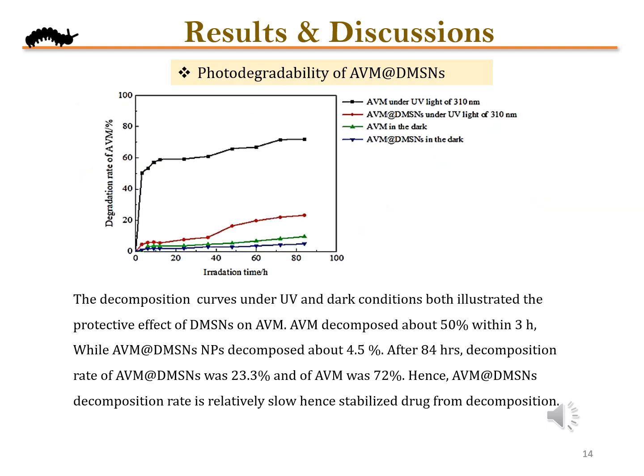As we know, the AVM is a photosensitive material. It was necessary to check the photosensitivity or the photodegradability of the AVM loaded DMSNs, and from the results it was shown that the decomposition curves under UV and dark conditions both illustrated a protective effect of DMSNs on AVM. AVM decomposed about 50% within 3 hours, while AVM loaded DMSNs decomposed only about 4.5%.